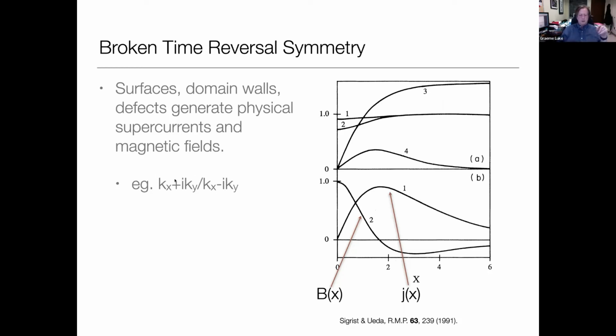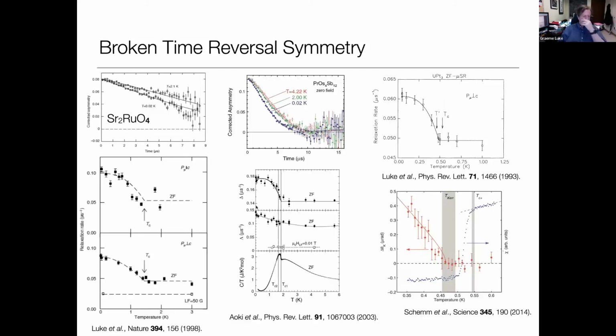So if you have a domain wall between two phases of the superconductor, if you have a phase that changes with distance, that rotating phase requires a current. And so you get a Josephson current, which flows along the boundary between the different domains. And those physical currents will make a real physical magnetic field, which you can then detect. So we've done this in strontium ruthenate. Here you see the relaxation rate above TC is small due to the nuclear dipole fields, and you see a relaxation which turns on below TC. You can see that there, and that shows you that your superconductor has broken time reversal symmetry.